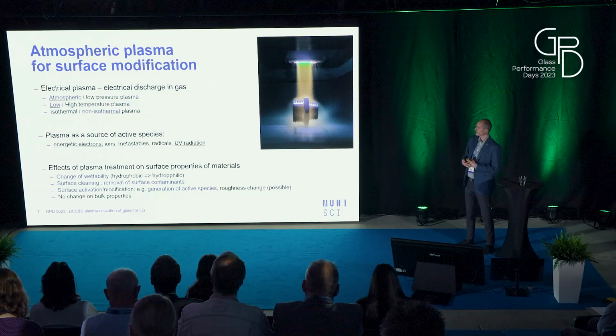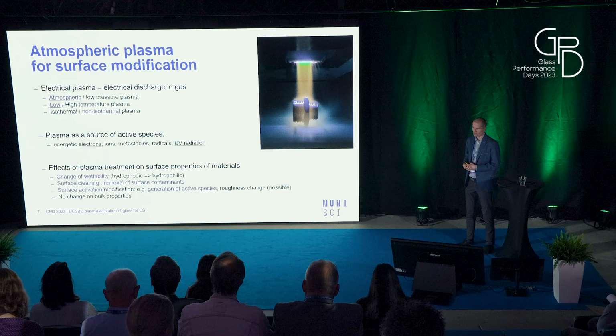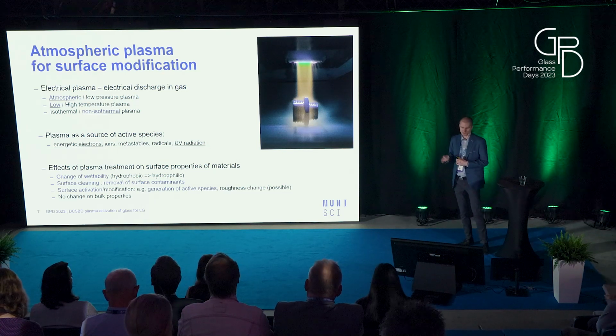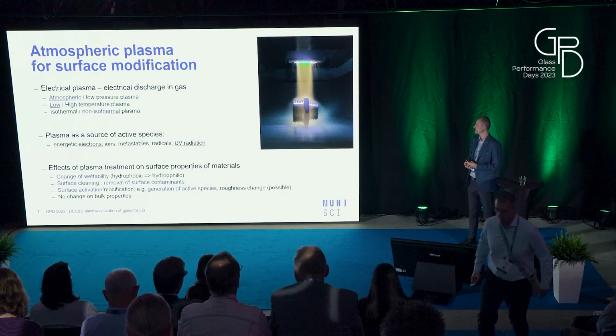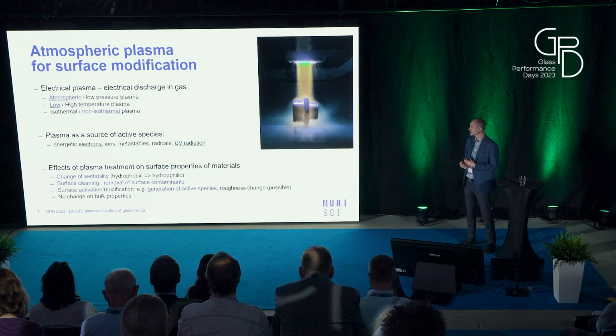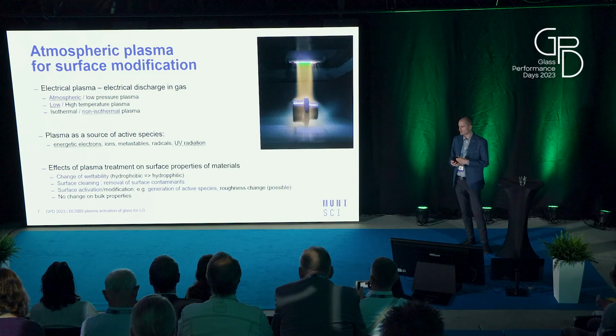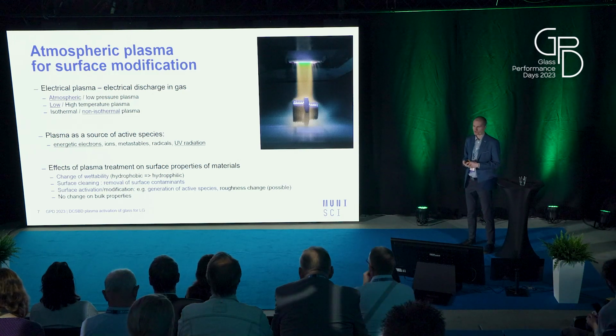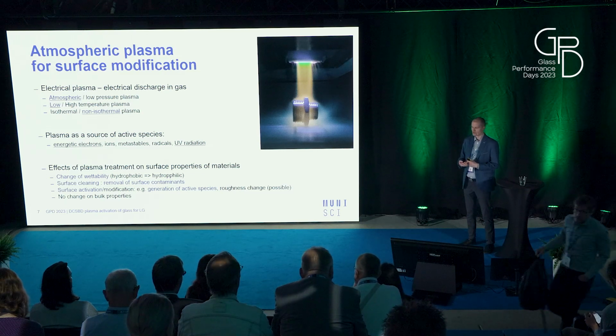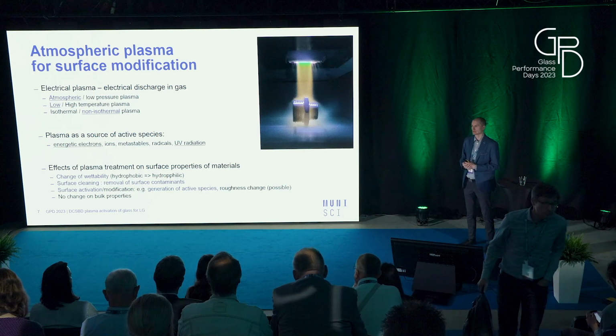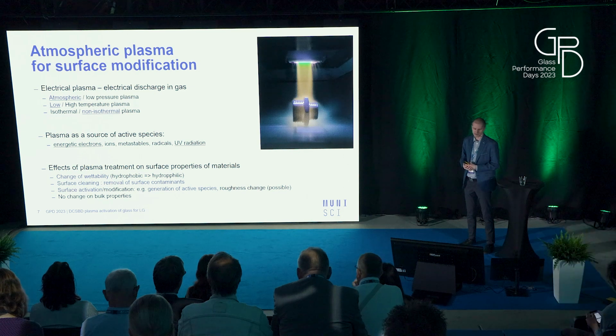The effect of plasma on the material includes various effects. We can change the wettability, for example, change a hydrophobic surface to hydrophilic. We can clean the surface, for example, by removing some surface contaminants. And we can also do some modification or activation, in the way that we create functional groups, which can then improve the adhesion, for example, to interlayers, especially in laminated glass.